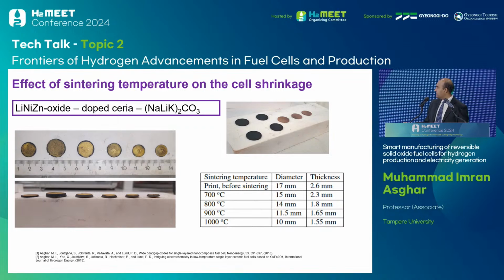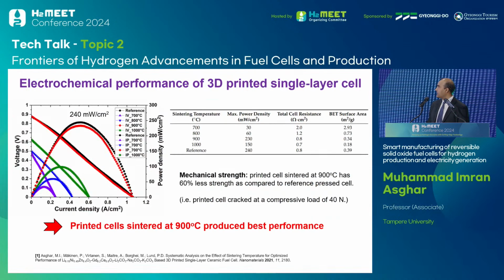So we print our cells with 17 millimeter diameter on the lab scale, and then we do sintering at different temperatures. When we increase the sintering temperature, there's more shrinkage of the cells. What we found out here is that the cells which were sintered at 900 degrees gave us the best performance. Another issue for cells manufactured by additive manufacturing is their mechanical stability.